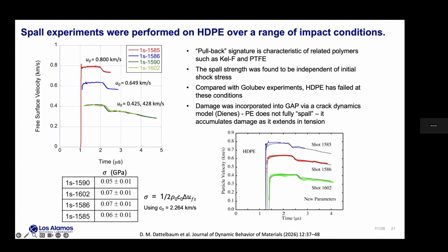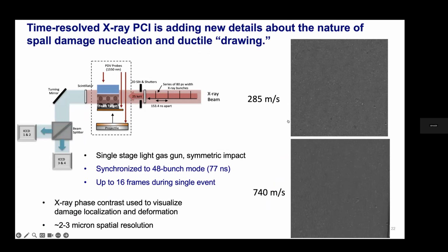Our initial modeling of this several years ago was using that gap model, but adding a crack model into it to capture failure. We know that this is not brittle behavior, but we still used a crack model that was developed by John Dienes many years ago at Los Alamos, which formed the basis for ViscoSCRAM. And I just want to point out what we're doing now, which is over the last few months, we've observed in situ spall damage of the polymers using X-ray phase contrast imaging, again at the APS, at the dynamic compression sector. And I believe it's the first time that we've ever observed this and done a scientific study as far as what the damage looks like in real time.